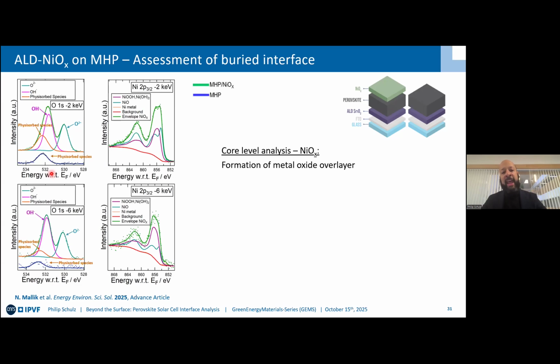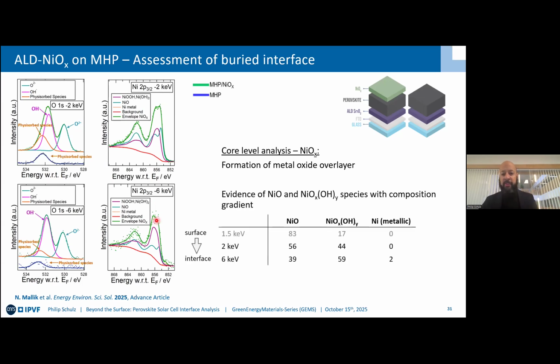And this goes hand in hand with the nickel 2p core level. It's actually not that easy to decompose. There is a procedure proposed by Mark Biesinger to identify the different phases of nickel oxide and nickel hydroxide, and we see a much more significant amount once we go to the 6 keV measurement. That means the nickel oxide that is closer to the interface. So you can do this for the different photon energies, and then you make the ratios of nickel oxide, nickel oxyhydroxide, and even metallic nickel. And you can see, as you're getting more and more interface sensitive, the ratio of these defective species rises.